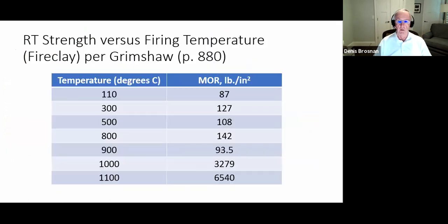Nevertheless, strength measurements are important. The reason they're important is strength increases as you fire the ceramic. So here's some data from Grimshaw. It's an old book on the chemistry and physics of clays. This was for a fire clay ceramic. And you can see strength values at various temperatures, and they're pretty uniform until you get up in the area of about 1,000 degrees Celsius. And at 1,000 degrees Celsius, we've actually performed some reactive sintering. There's been some melt formed and new minerals formed between the fire clay particles. And as we continue increasing the temperature, we're going to get very dramatically higher strength.